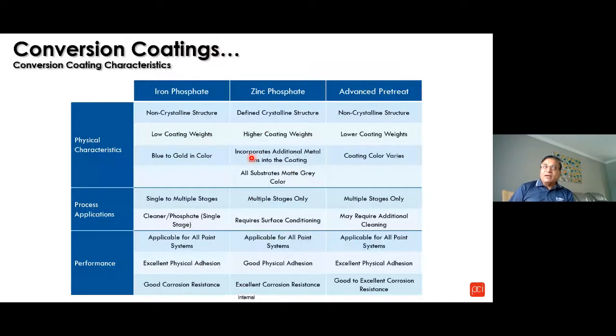Let's take a look at some of the comparison on the coating side of it. You can read through, I won't go into the detail. The physical characteristics, the process, and the performance of it. I'd like to spend a little more time on the performance side rather than the coating weights. Iron phosphate is typically from 30-50 to about 70-75 milligrams per square foot. Zinc phosphate is about 250-300, and zirconium pretreatment is a low coating weight, which is why it's called a thin film. It does not do as much etching as iron phosphate and zinc phosphate do. That's why it does not produce as much sludge, or virtually no sludge.